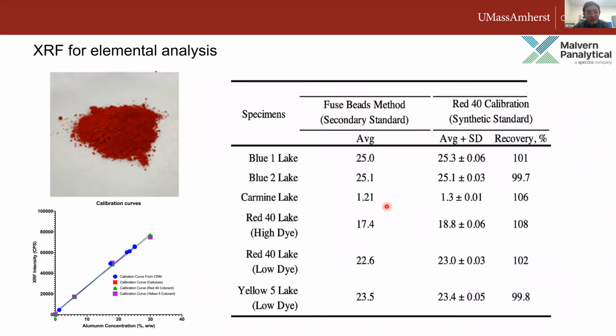Another application we made is to detect aluminum content in artificial colorants. In this case, the aluminum concentration is at the percentage level, which falls into the detection range of XRF. And as we can see here on these figures, it presents a very good linear relationship, and the recovery is also pretty good for detecting aluminum.